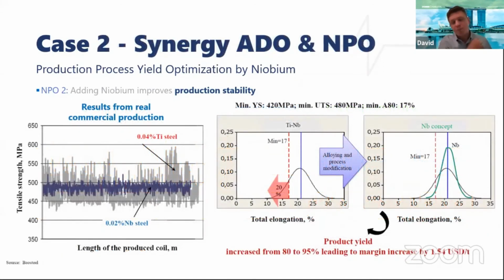Another great example of that comes from Baosteel producing automotive sheet. This is a 420 HSLA grade for cold rolling. And they still used to be produced with 400 ppm titanium addition due to alloy cost reasons. And the graphics, you can see the points in gray show the titanium steel and its variations of tensile strength. And this steel was changed to a 200 ppm niobium concept. And you see that the variation of the mechanical properties along the length of the production coil is a lot smaller. This is translated into elongation as well.